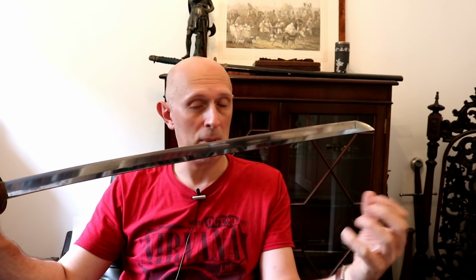Now, there are two peculiar things about Japanese swords which we need to highlight there. Number one, the fact that they cover some of the blade in material before they quench the entire blade, so therefore you are hardening the whole blade, but you're hardening the edge more, and that's what gives you the characteristic hamon, which is the sort of whiter coloured edge to a Japanese traditionally made sword blade, which is harder than the rest of the blade. So hence the name differential hardening or differential quench, whereby the edge, both by virtue of being thinner, so therefore it cools down quicker, and by virtue of not being covered by clay, cools down a lot quicker. Therefore the edge is a lot harder than the back.